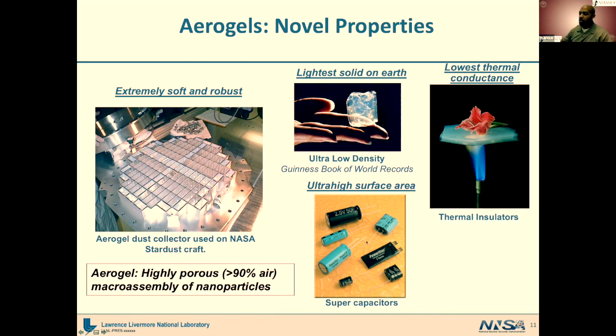And then coming more to the application that I work on, they have very, very high surface area. If you combine that with the high conductivity of carbon aerogels, you have a recipe for something like a supercapacitor. Back in the 90s, they actually did commercialize the Power Store supercapacitor, which was used in the PlayStation, might have been PlayStation 2 at that time. So they are commercially relevant.